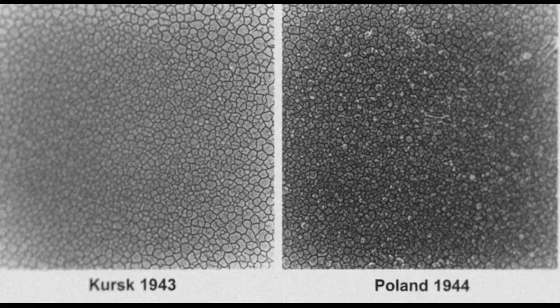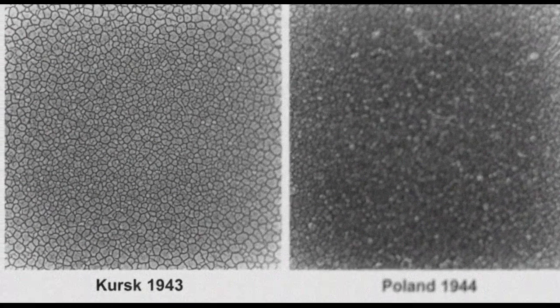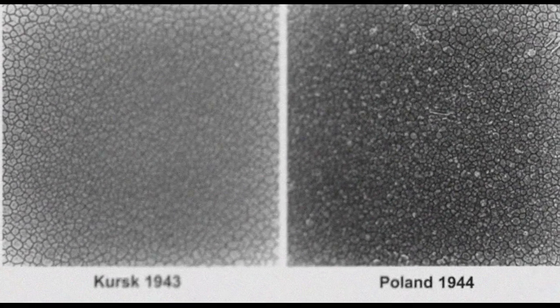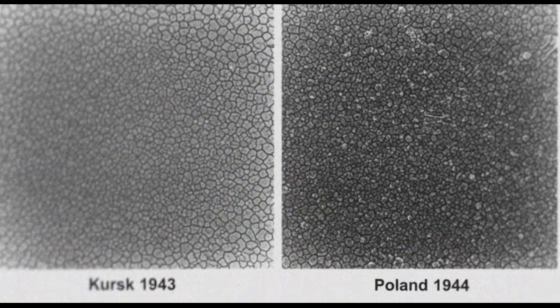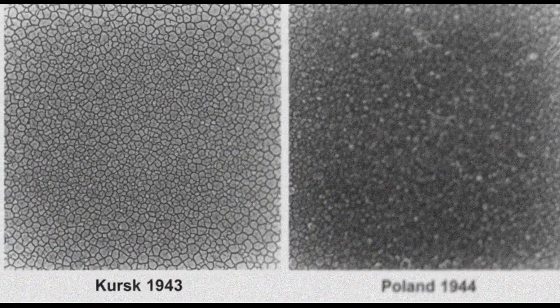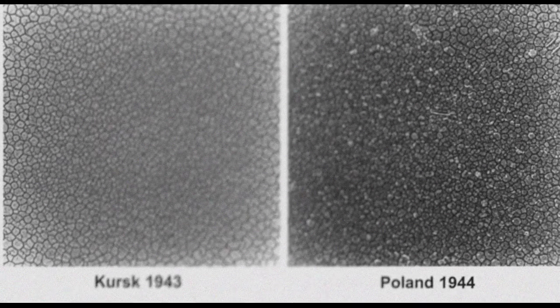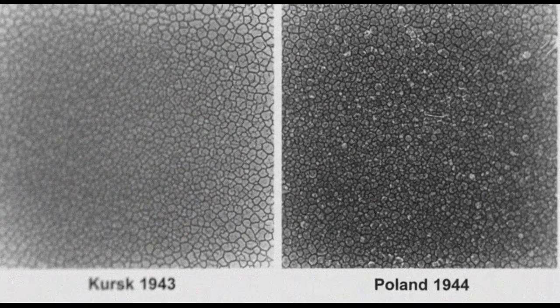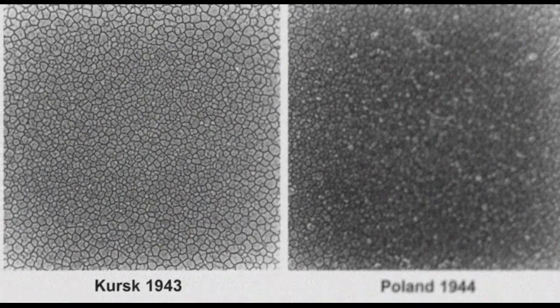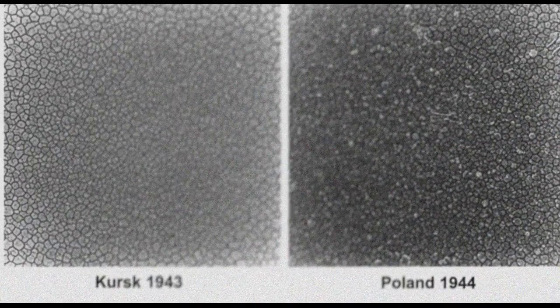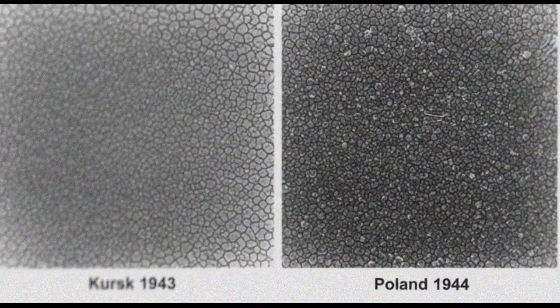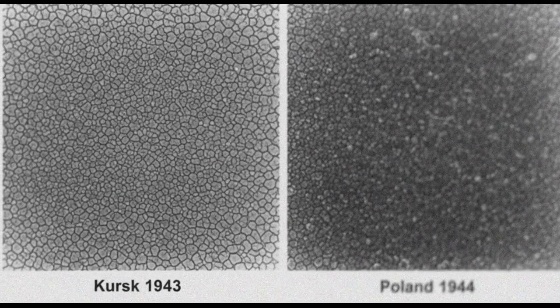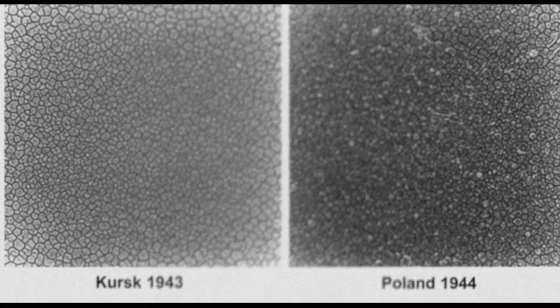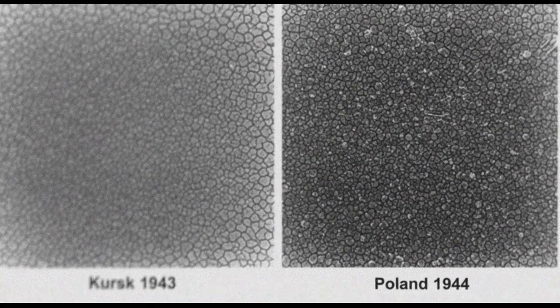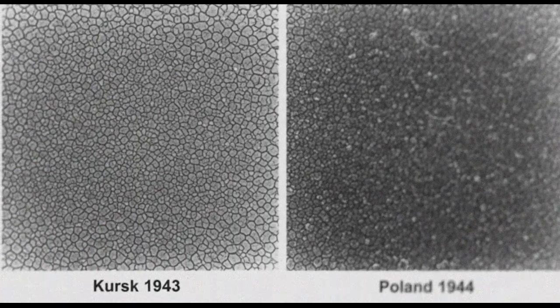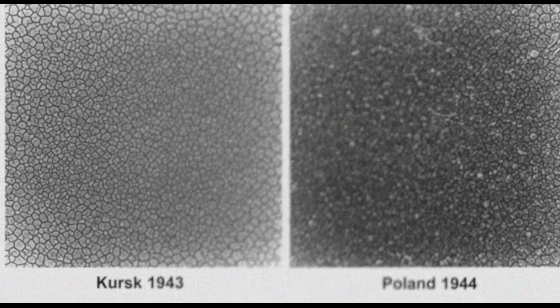But as more samples arrived throughout 1944 and into 1945, a pattern emerged that could not be explained by simple manufacturing variation. The quality of Panther armor was declining, and it was declining rapidly. By mid-1944, Panthers recovered from destroyed tanks showed armor that was brittle and prone to cracking. Some plates showed evidence of poor welding with seams that could split under stress.